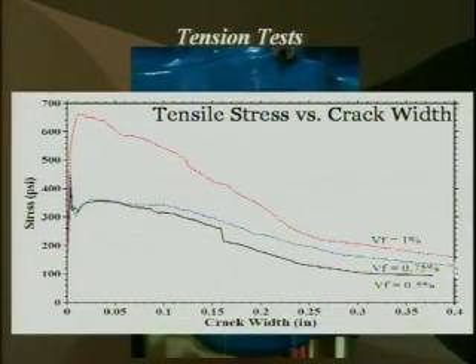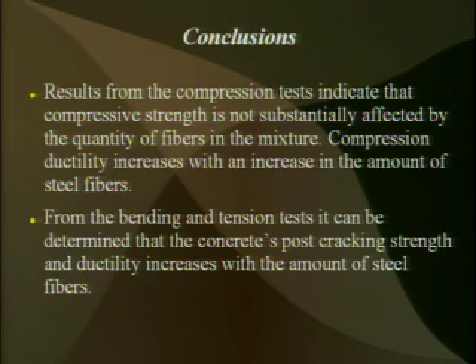As I mentioned previously, these results were similar to the ones in the bending test. The post-cracking strength and ductility increased with the amount of steel fibers in the mixture. Finally, results from the compression test indicate that the compressive strength is not substantially affected by the quantity of fibers in the mixture. Compression ductility increases with an increase in the amount of steel fibers.